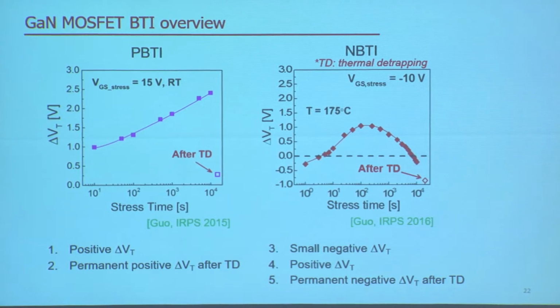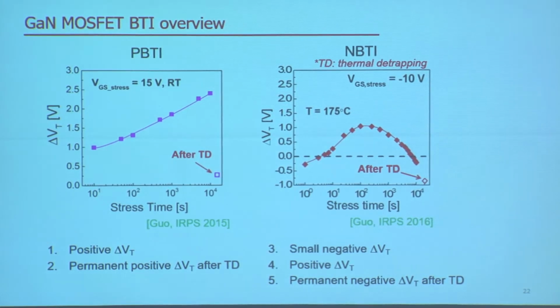On the left side is the typical behavior of PBTI, and there are two regimes of behavior here. So what you see is that when we apply a positive gate bias stress, first we see a positive VT shift. You see the delta VT is positive. So delta is basically the change of threshold voltage, and it increases with stress time. And then this is the first regime. And the second regime is what happens after we thermal detrap the device, where we have a residual permanent positive VT shift that is not recovered.